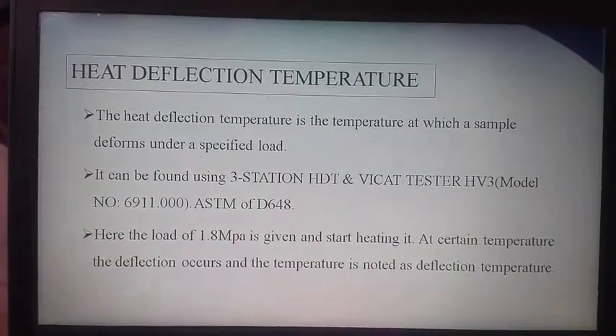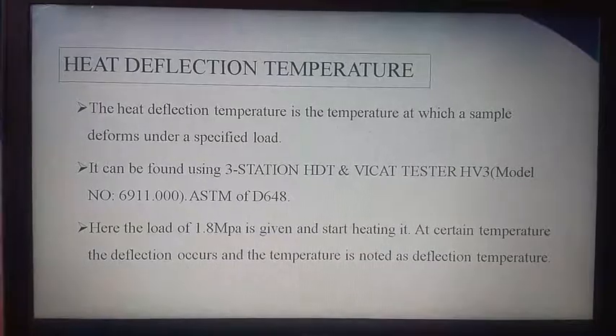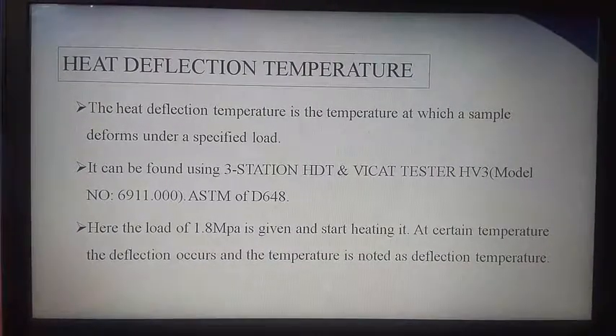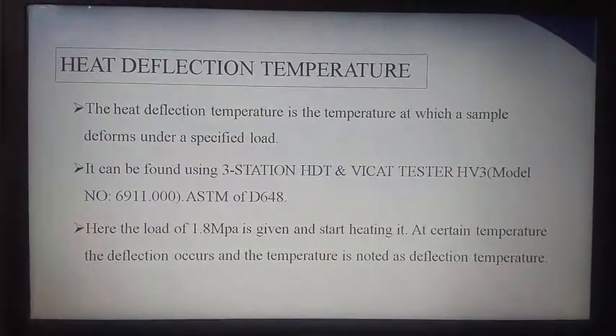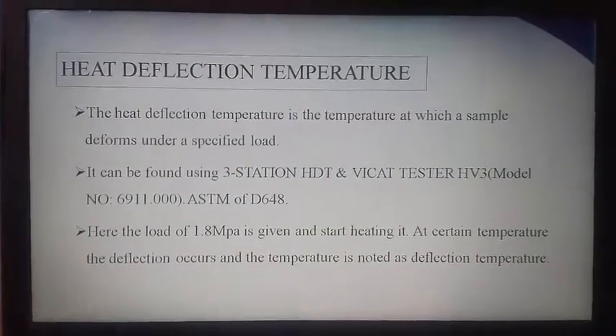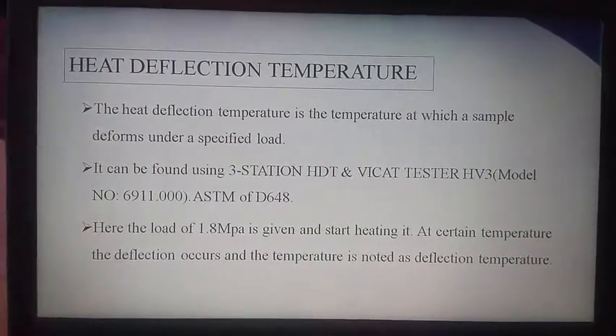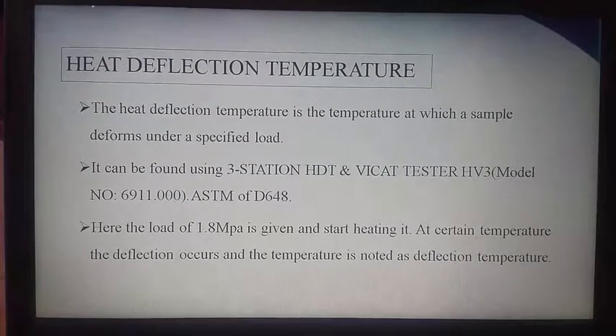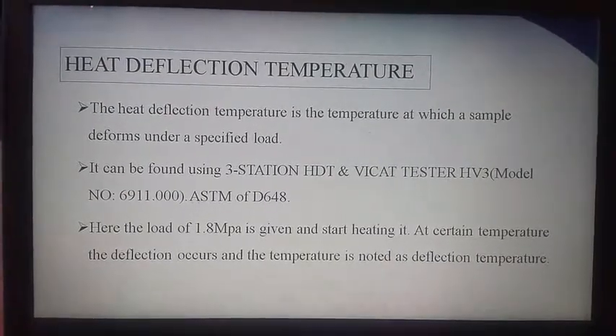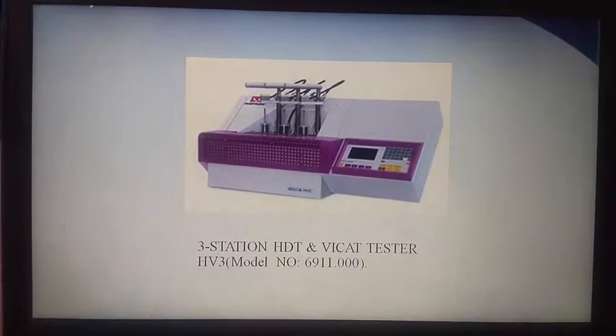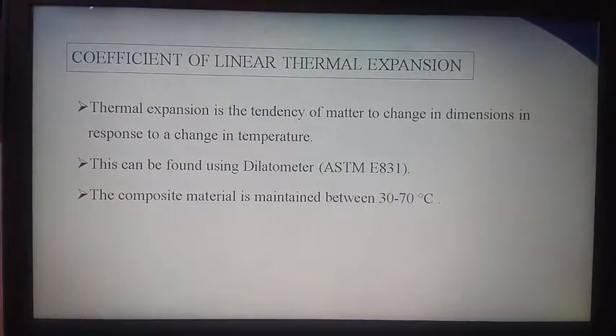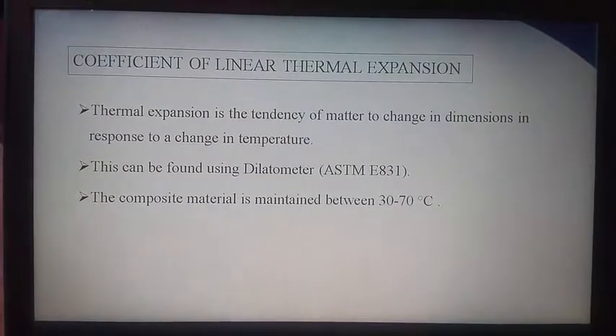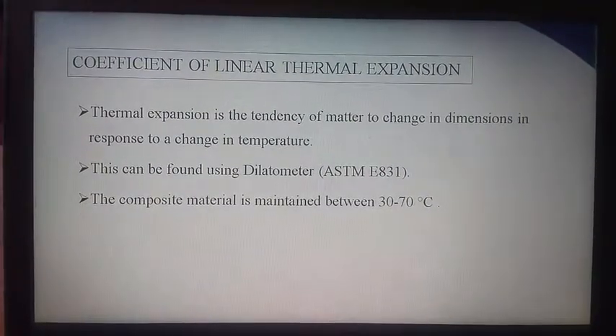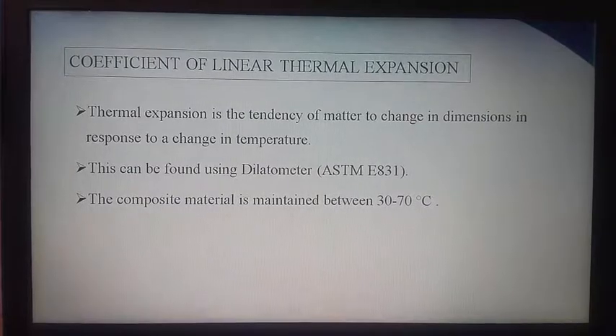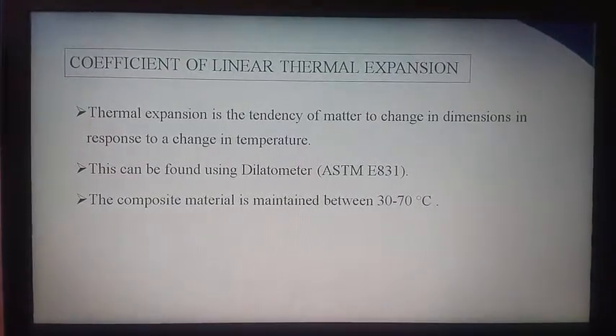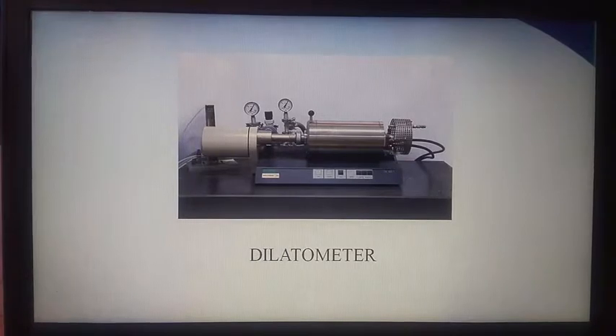Heat deflection temperature is studied using a 3-station HDT machine, and we test it under a constant load of 1.8 megapascals. This is the machine. For the coefficient of linear thermal expansion, a dilatometer is used to test this property, and we maintained a temperature between 30 and 70 degrees centigrade. This is the dilatometer we used.